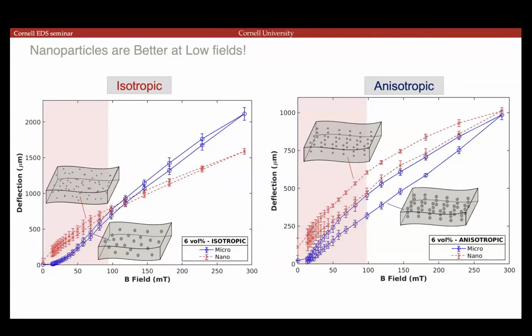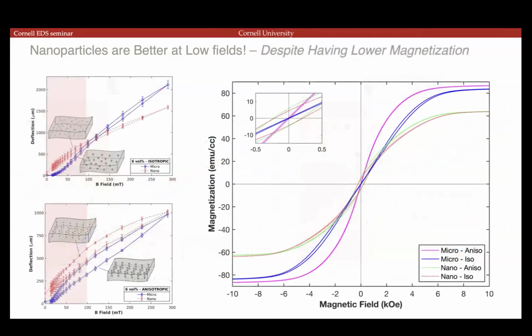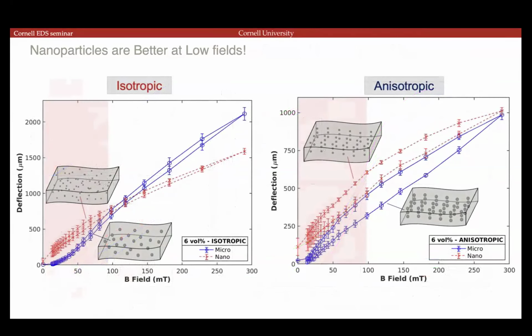Yeah, but the main reason is because these are soft magnetic particles, and we're not getting the increase in... actually, I think I have the magnetization here later. I don't think I included the description of why these are better, but the mechanism here is force and not torque. So it depends on how easily each of these is magnetized in the field and how much they deflect. There's a lot more.